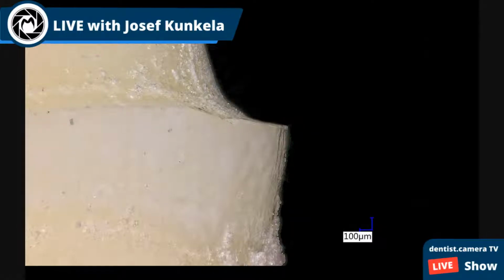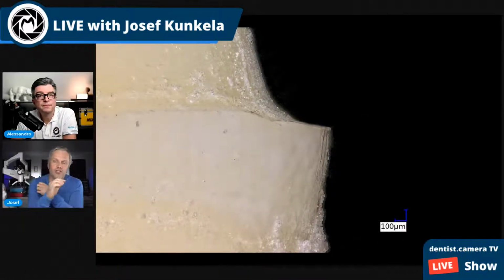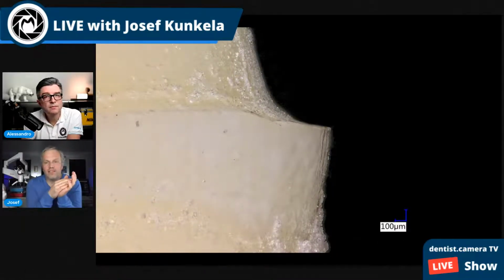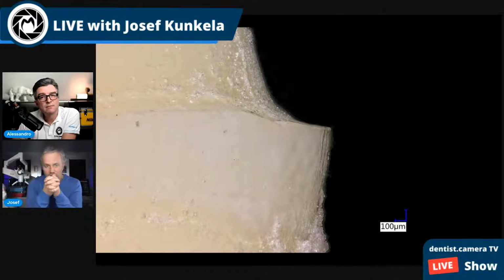If you choose the right instrument for the preparation, and you prep all the time with the red strip and avoid the green one or the black one, especially around the neck where there is a lot of aprismatic enamel, you can avoid cracks or chips of the enamel. And definitely if the margin line is not smooth, the milling unit and the printing machine cannot copy the margin line with a lot of cracks and chips around.